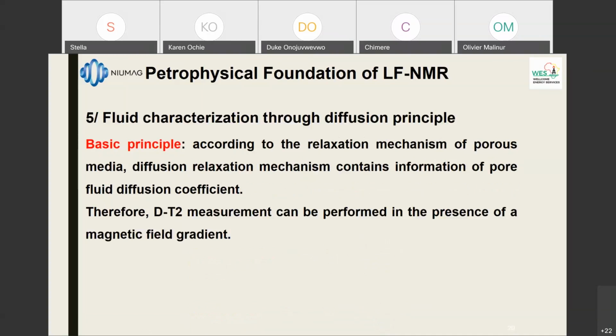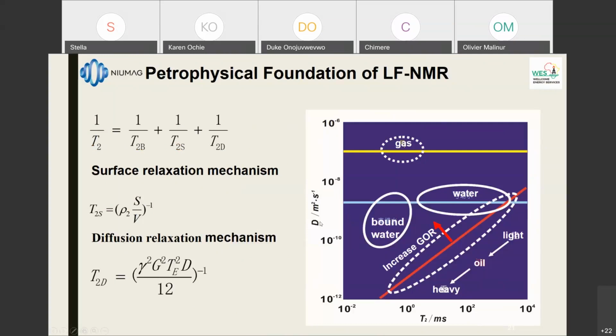The next information we get is the characterization of the fluid. We're able, through the graph from the diffusion and the T2, to find which type of fluid we have. So remember, we have the diffusion here, which is this term, and we have here the total T2, which is this term here. If we plot this versus that, you have one line here, which is purely depending on the T2, which is going to give us the bound water or the water. And this line, for finding the bound water and the free water, is depending only on the T2, and to find the line separating, purely on the diffusion.